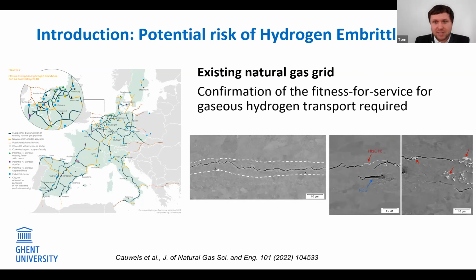However, atomic hydrogen can enter the microstructure of steel or other metal by dissociation of hydrogen molecules or by reduction of protons, for instance, in the case of cathodic overprotection. And this can lead to hydrogen embrittlement. This hydrogen embrittlement causes a variety of degradation modes in otherwise high-performance steels. Hydrogen is known to potentially increase the growth rate of existing cracks under cyclic pressure, deteriorate the fracture toughness, and also give rise to hydrogen-induced cracking when severe charging is applied. For instance, in this picture, you can see an X70 pipeline steel where cracks were initiated in the hard segregation bands showing MnS inclusions and niobium-based carbonitrides.